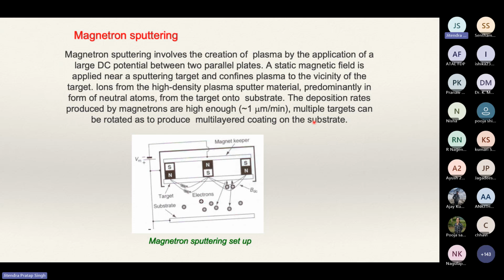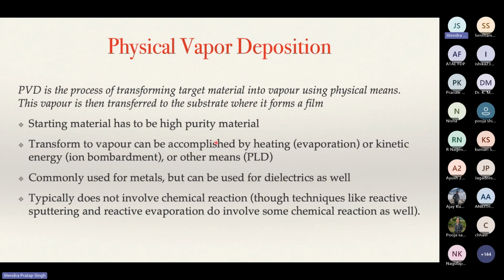So you can get the idea, a few angstroms per minute to 1 micrometer per minute is a very big change. Also, you see mostly in sputtering systems that these targets are rotating, and the idea is to have uniform deposition so that there is no kind of hole formation, and uniformly the target gets sputtered out from the plasma and deposited on the substrate. This is just giving some idea of what kind of thing is there. Then in sputtering there can be multiple sources, multiple targets also. So one can think of co-deposition in magnetron sputtering. You can deposit more than one material in a single chamber. So that was basically the idea about sputtering.